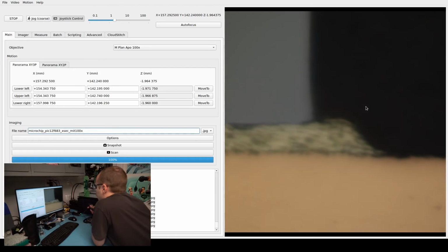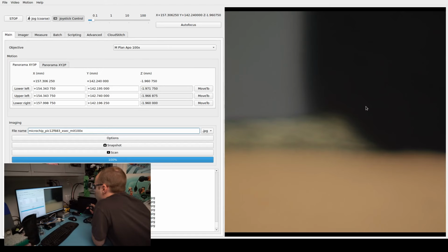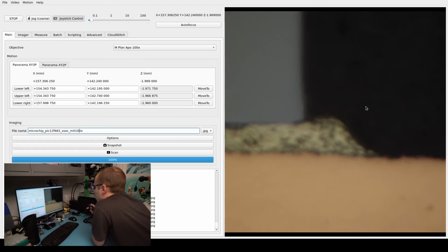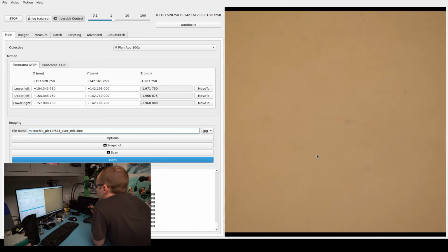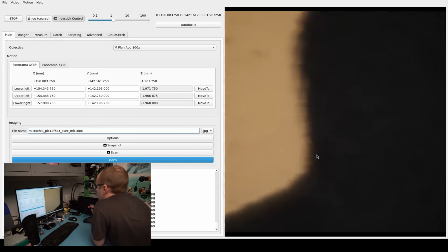And then moving down to the bottom right, we've got a little bit more of the die attached. This is again the bottom right corner of the die attaching to the paddle, and we can see a little bit of the surface roughness on the paddle. It's probably etched or sanded in some way to increase the roughness so that it attaches more firmly.